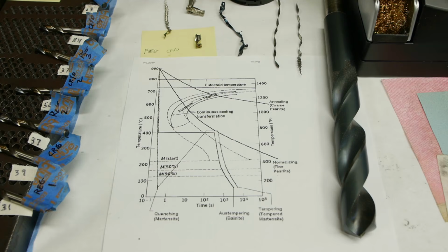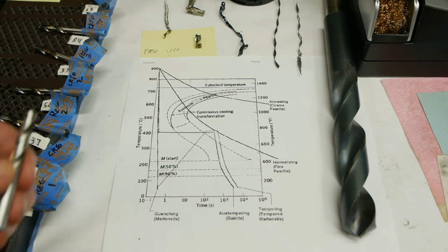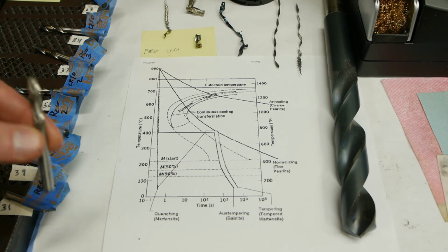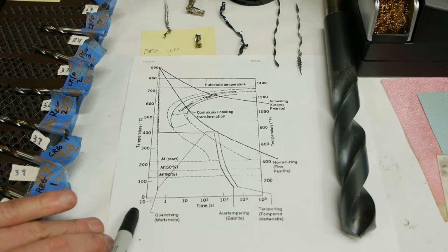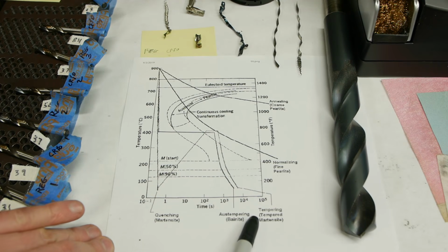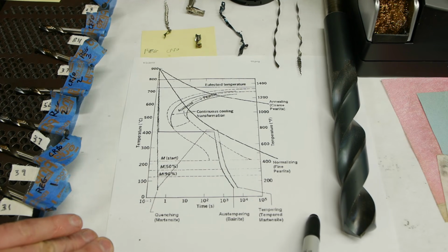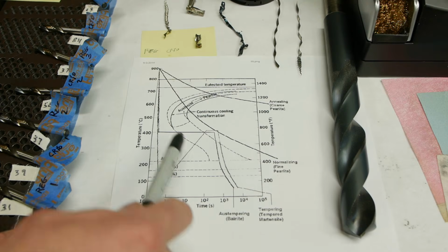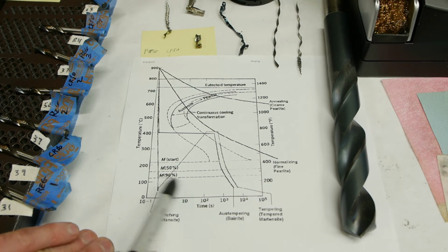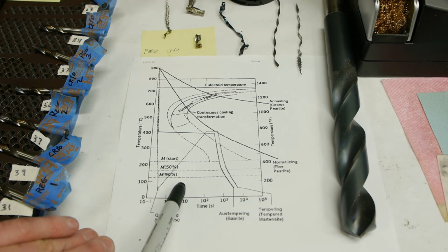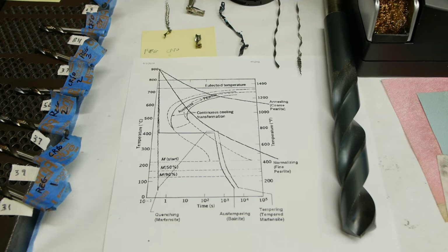But actually, as it turns out, no, it's still changing. The steel is still able to be modified by temperature. And you can see on the graph the time is actually logarithmic. So we could be out at 10 to the 8th seconds or whatever, and you can still get it colder and still convert more of the structure to martensite. So basically, what's happening is we're just finishing off the heat treatment even after the steel has been tempered, which